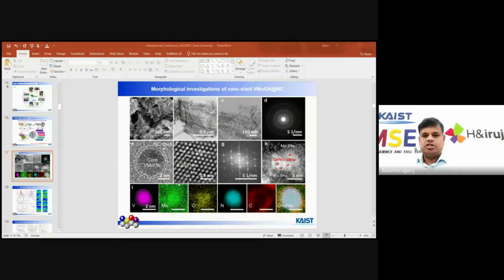You can see this is the zoomed view of the core vanadium molybdenum nitride and the shell NC, that is, nitrogen-doped carbon, and there is a numerous amount of molybdenum from the STEM only. We can see the molybdenum single atoms throughout the graphitic networks, and we also see the homogeneous distribution of molybdenum, oxygen, nitrogen, and carbon. This further proves the homogeneous distribution of the elements, and the molybdenum is throughout the area, while the vanadium and nitrogen are only present in the core. Vanadium is not present as a single atom; only molybdenum is present as a single atom, therefore it is spread over the area of the graphitic networks.